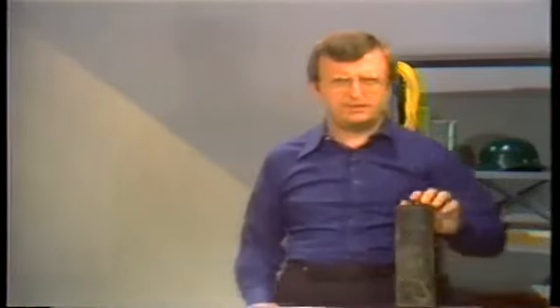Overheating in the water wall tubes leads to warping, leaks, and tube blisters. Warping is caused when a section of the water wall overheats. This is fairly easy to spot. It may be indicated by a large number of leaks in a small area of the water wall. Now, tube blisters, like these right here, are bulges in the tube surface, which form when the tube metal becomes so hot that it softens and is pushed out by the boiler pressure.